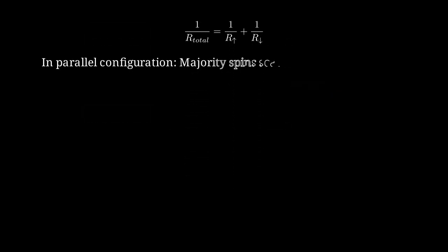In the parallel magnetic configuration, majority spin electrons have low scattering because they see aligned magnetic moments everywhere. Minority spins scatter strongly, but the low-resistance majority channel dominates. In the antiparallel configuration, both spin channels encounter alternating layers where they are majority then minority. Both channels scatter strongly, roughly half the time. The overall resistance is much higher.